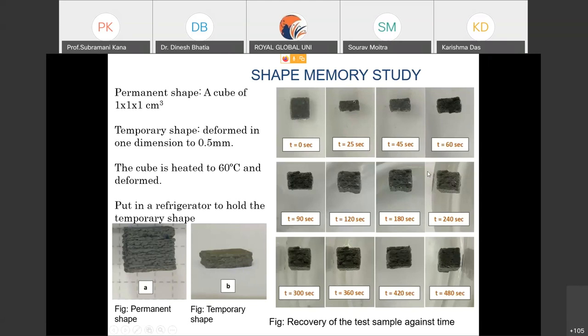you can see here, at each and every time we have observed how the sample size is getting enlarged. Then after 120 seconds, it is more or less the approximate size of that initial sample. Then the density got decreased because the size increased, and it started to come up from the bottom and float. It has come nearer to the top of the beaker. Then after 180 seconds,